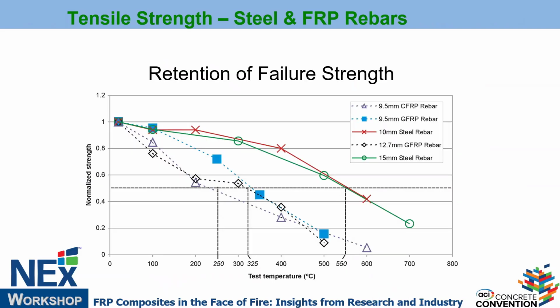So, we also did, as I said, the problem with FRPs is different types, different GFRP materials. So, all this is a problem. So, we did this for Canadian PWGSC, Public Works. They used in the Canadian Parliament building slabs with GFRP. So, at that time, we compared here the normalized strength, 100% at room temperature, versus temperature. As you can see, this is the steel. So, at 550 degrees centigrade, steel loses about 50% of its strength. That's very helpful for defining failure in steel. That's called the critical temperature.